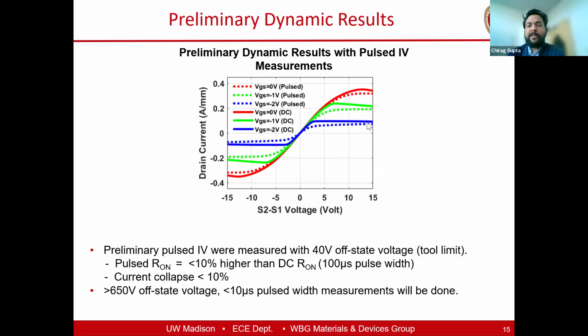And the fact that the degradation is not significant also tells us that our field plates are doing a reasonable job. We are probably not using surface traps for spreading the field in these devices, but again, we need to go close to 600 volt or 1200 volt in the off-state pulsed IV or dynamic on resistance measurements to get a better sense of where we are.